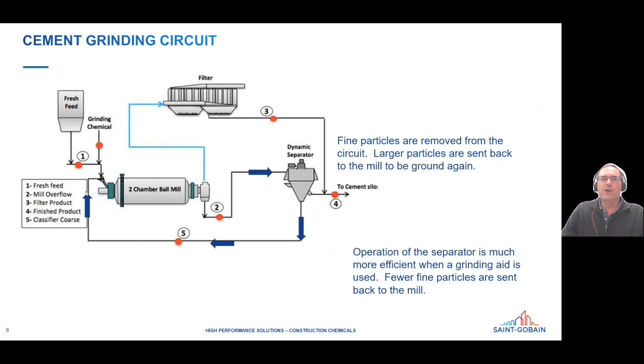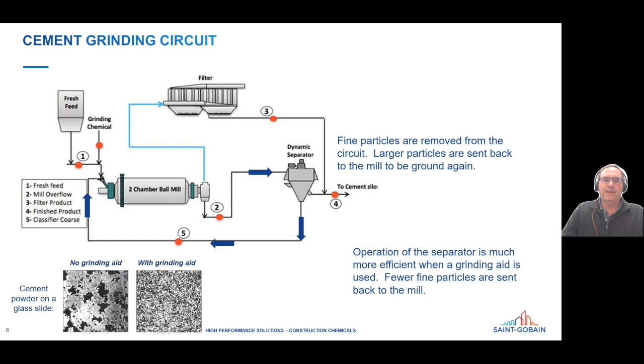When you use a grinding aid, the separator works much better. What happens actually is the grinding aid acts as a dispersant. So it actually removes all these agglomerates, breaks them up. And so the fine particles then are actually treated separately. They're actually carried in the air separately. And so the separator is able to take them out.